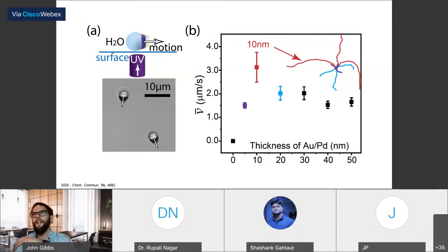However, for something like 10 nanometers, it's pretty well known from the literature that when you deposit using physical vapor deposition, you get these islands, right? So we think we have a much larger surface area, with gold islands decorating the tops of the TiO2. In that case, it can greatly enhance the catalytic behavior. So this was just a follow-up study on that.